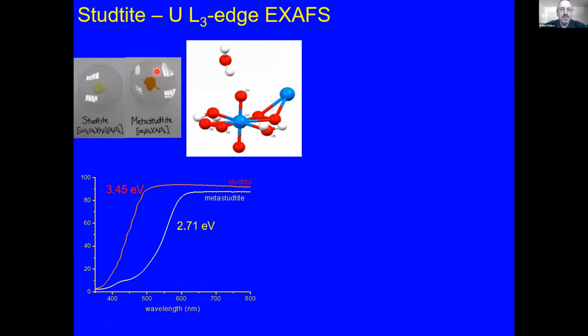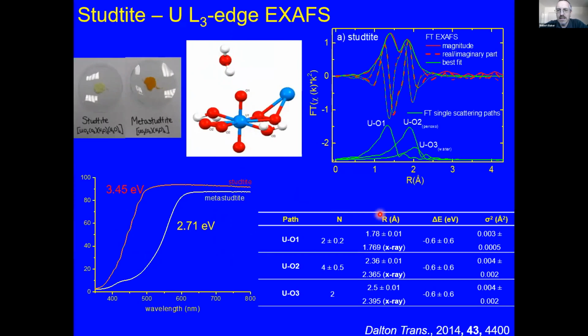So we were able to synthesize studtite and metastudtite in the lab really easily. And what's really surprising as a coordination chemist is the difference in the colors, which is also shown in the band gaps from the UV spectra, because all we're doing is removing these waters of coordination. So how can you change something so drastically by just changing the coordination waters? So we started looking firstly at the structures of these compounds. Now, as everybody does, you go to a mine in Zaire and dig out a crystal and stick it on your diffractometer. And this happened, and the X-ray structure of studtite has been reported.